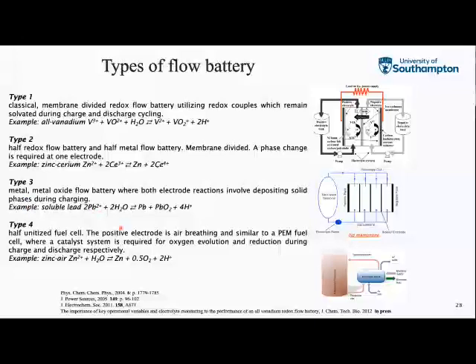The third type is a metal oxide. So the example would be the soluble lead. There you've got a phase change at both electrodes. So at the negative electrode, you're going from solvated lead ions to metallic lead during charging, and the positive electrode, you're going from solvated lead 2 ions to solid lead dioxide at the positive electrode. So a phase change at both, and that means that the charge state physically separates the lead dioxide and the lead. So you only need a single reservoir because there's no chemical contact between the two charged species. So there's no chemical self-discharge.